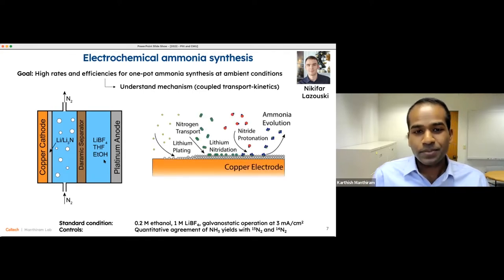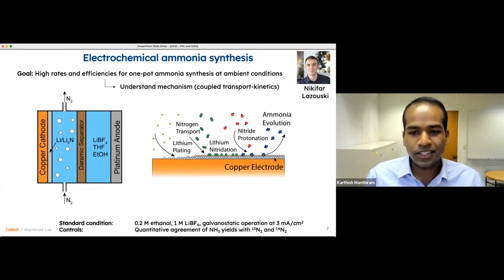And so all these steps that are needed ultimately to make ammonia are occurring simultaneously on the electrode surface. We're plating lithium ions to make lithium metal. That lithium metal reacts with dinitrogen, which comes to the surface and dissociates. That then gets protonated, making ammonia, and that comes off the surface. And one can operate then galvanostatically at several milliamps per centimeter squared and higher, as I'll show later.